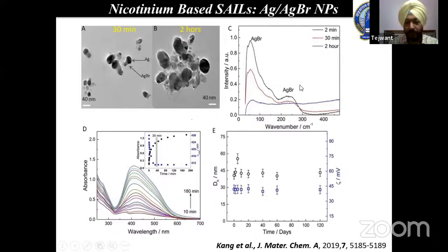Further, the formation of silver bromide has been established from Raman spectroscopy. One can see that in the Raman spectroscopy, the band for silver bromide is very much higher for the sample found at 2 minutes of irradiation. Once we increase the time from 2 minutes to 30 minutes and to 2 hours, the peak for silver bromide goes on decreasing. This shows that the silver ions get reduced as you increase the time period.